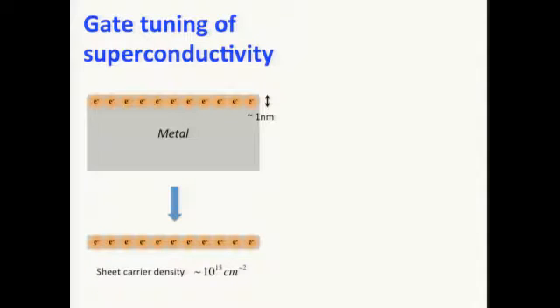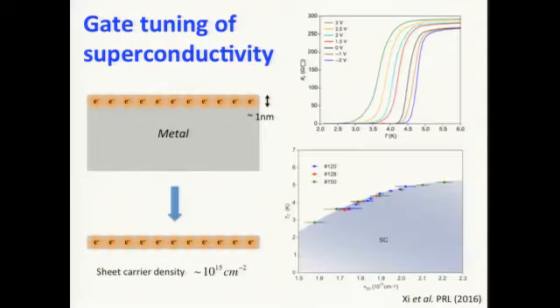Except that it does not explode in our device. Then we can actually tune the TC by 30–40%, quite significant tuning using a few volts of gate voltage. And this is actually the phase diagram we got from this kind of device. This is actually a bilayer. It's pretty hard to do it in a monolayer.